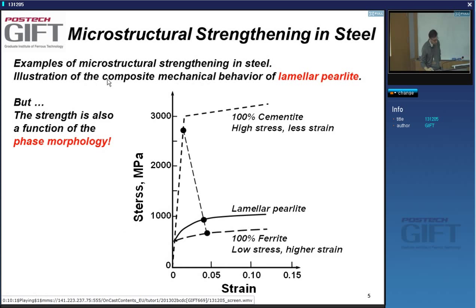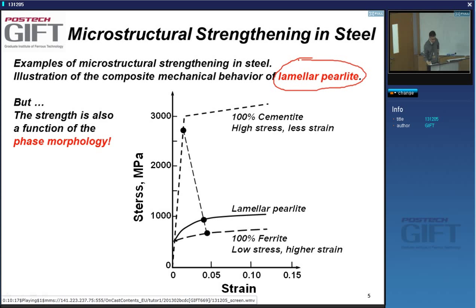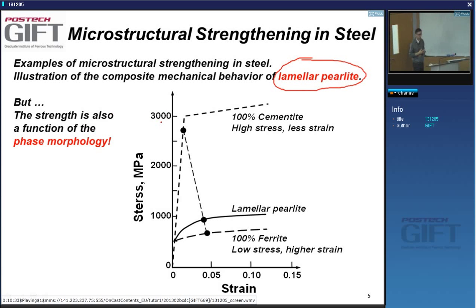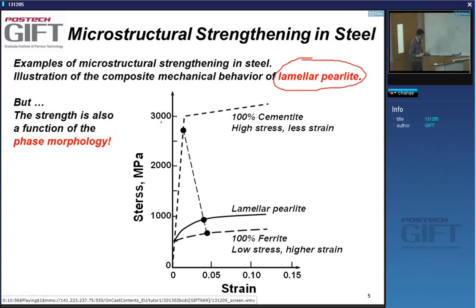There's something interesting about this phenomenon and about pearlite — in particular, the fact that we have lamellar pearlite. That's really important. If I have pearlite, I have basically two phases, and this reminds you of a composite. It's actually a very nice composite material. To understand the behavior of the composite, I need to look at the alpha phase — the ferrite — and the theta carbide, which is another way of saying cementite.